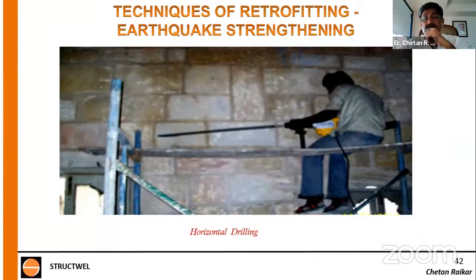Now, your immediate question could be, how did you grout 1.5 meter of epoxy? So we actually used long pipes. And by removing the pipe while grouting, we were able to fill the space and insert the rod quickly. So we drilled this through the openings, you know, the sides of the door and sides of windows and things like that. So we did horizontal drilling, inserted the reinforcement up to 5 feet. So three stones we were able to stitch together. Again, this is in the mid thickness of the wall. Same way for vertical reinforcement also.